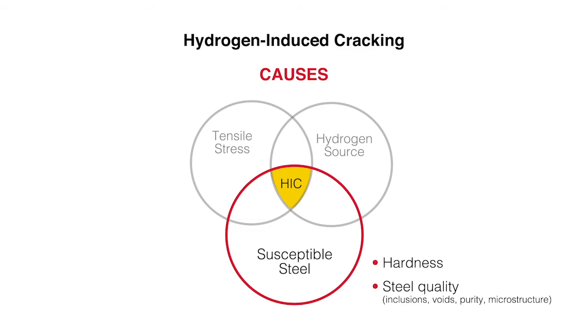For the manufacturer, the steel design is really where it all begins. There are three main factors to consider: first, the grain size; then the carbon content; and then the alloys that go into the steel. By decreasing the grain size, decreasing the carbon content, and adding different alloys into the material, you can create a steel that is resistant against hydrogen embrittlement while at the same time retaining higher strength.